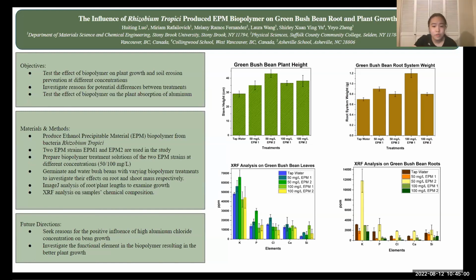The XRF data also reflects this difference, as the 50 milligrams per liter EPM2 treated group has the highest concentration of potassium and phosphorus in both the roots and leaves, as well as exhibiting the best absorption in the roots for all analyzed elements. However, the higher absorption did not help with root development as indicated by its mass. Both EPM1 treatment groups have the larger average weight of the root system than the EPM2 treatments, with 100 milligrams per liter EPM1 treatment showing a larger positive influence on root development than the EPM2 treatment of the same concentration, with a p-value of 0.028.